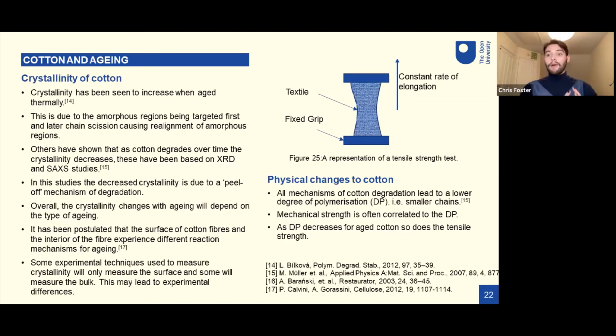So moving on from how the fibre appears, I want to talk about how some of the properties change. And first, I'm going to mention crystallinity. Now, the crystallinity of cotton has been proposed to have different effects by different studies. Some studies have shown that with thermal aging, there's an increase in crystallinity. And these studies used infrared and Raman spectroscopy. This increased crystallinity with aging was put down to those amorphous regions, so the disordered regions, being targeted and chain scission occurring, so that breaking of the bonds. And this was causing realignment of the amorphous fibres. So they're actually becoming more ordered and more crystalline, leading to a more crystalline fibre.